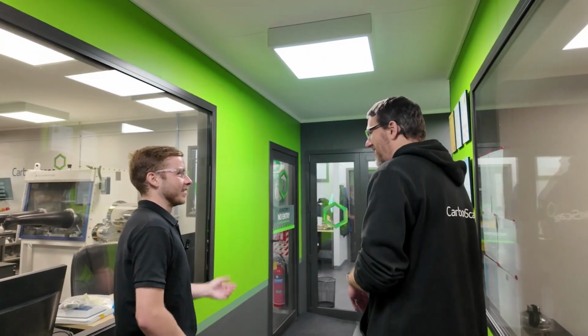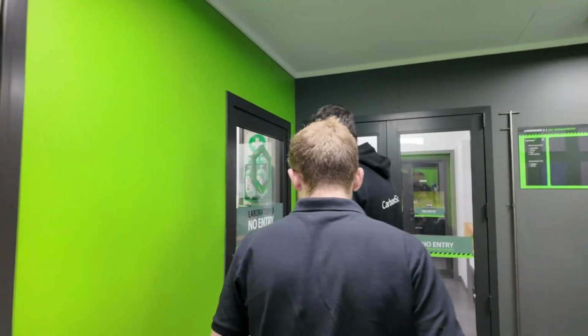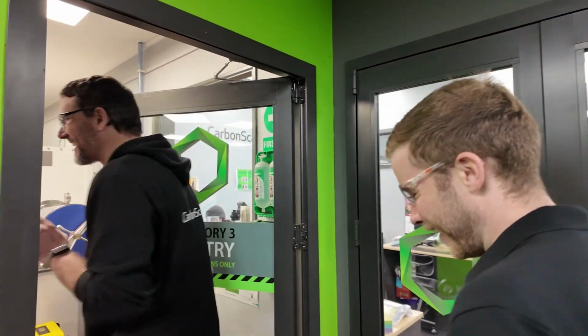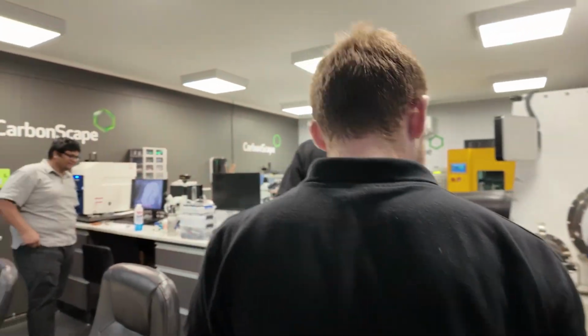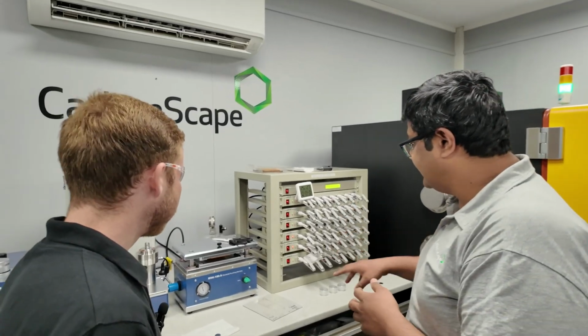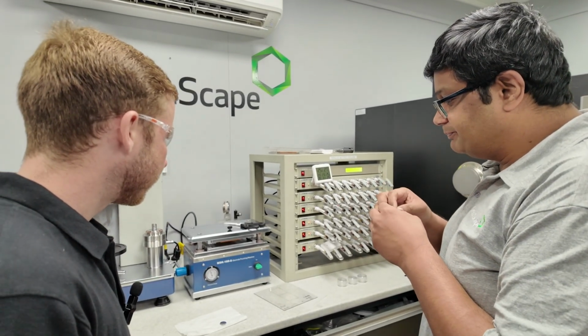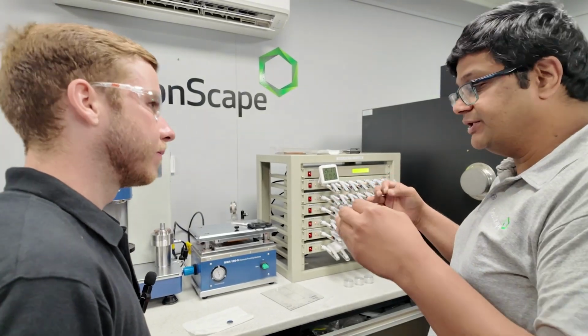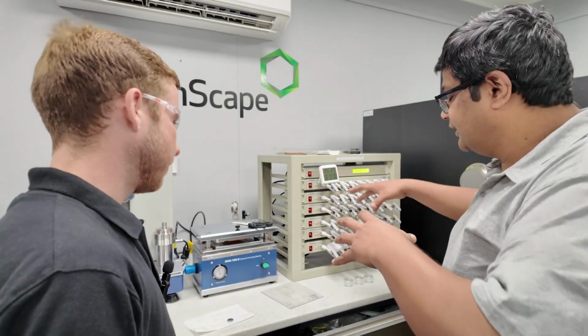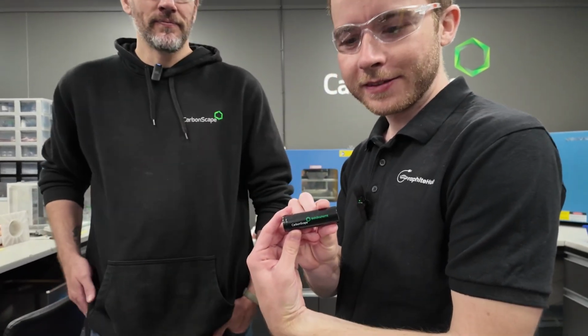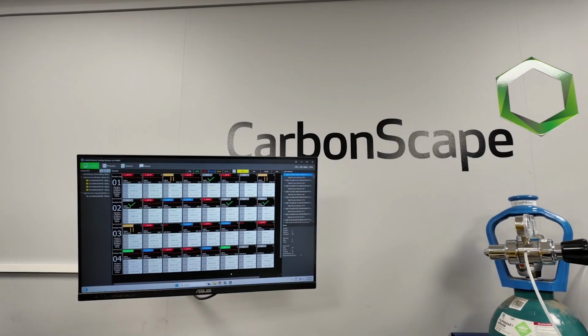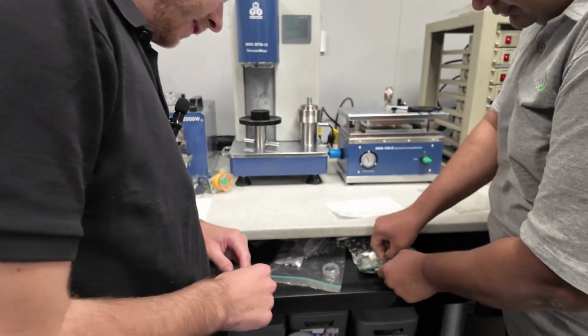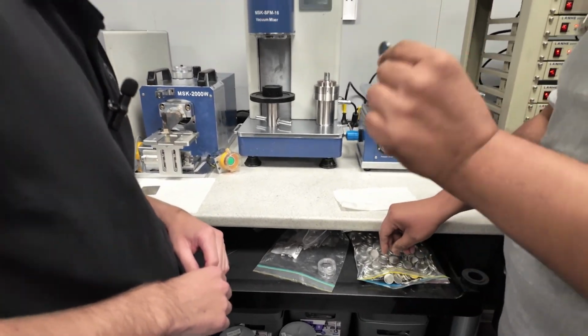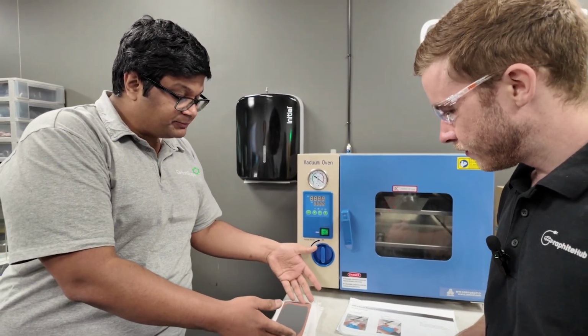Coated graphite is only half the story. The real test is how it performs inside actual cells, and this is the lab where it happens. The team prepares a slurry from the graphite powder, coats it onto copper foil, and assembles coin cells and small pouch cells to evaluate performance. Once coated, the foil becomes the anode, which is then paired with lithium metal to measure capacity and first cycle efficiency. Testing begins with coin cells before moving on to pouch cells, and from there they scale into larger cell formats to confirm the material performs consistently at every level.